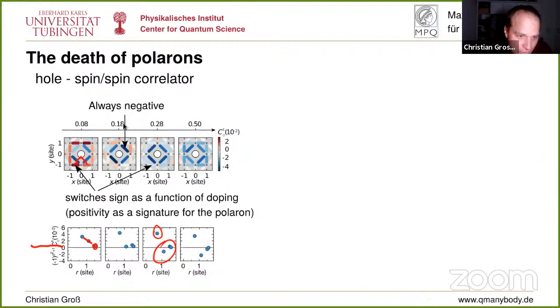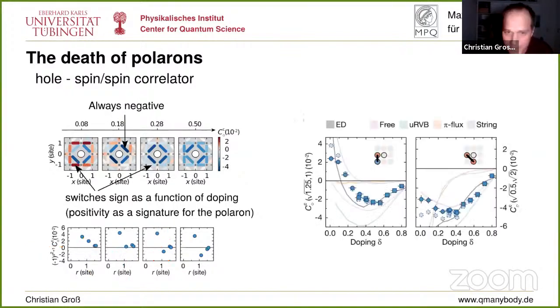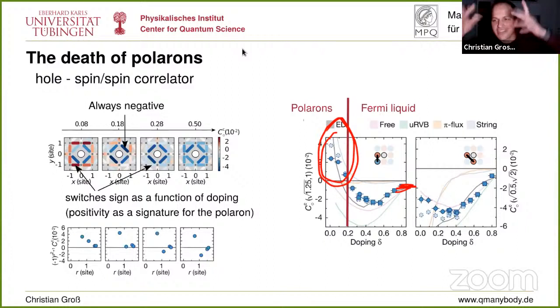And now, to make this again more quantitative, we look at that point where we have the best signal, right? And track that versus doping, and that is what is shown here. Well, I think it's 2 points that are shown. So this one here is the first point where not much dramatic happens. We see a little bit the amplitude changes, and this point which really changes sign is this correlator here that is illustrated here. That really makes this change from being polaronic, right? So it has this opposite correlations here, and then being at the same sign that it also asymptotically has in the Fermi liquid. So if you want to call something very roughly the bound where basically polarons die, then you could say that might be where that correlator changes sign and goes away from the value it has from the polaron side to the Fermi liquid side, so to say. So it's basically what I say is the hole doesn't mess up the correlations enough anymore from this point on.